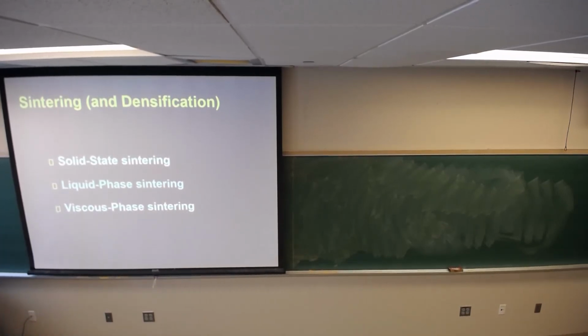Now if I get small amounts of impurities, then I get a liquid phase in the system, and that liquid phase facilitates the sintering process. It is my opinion that everything we see in ceramics is very likely liquid phase sintered. Everything. Well, now we have a bit of a disconnect.